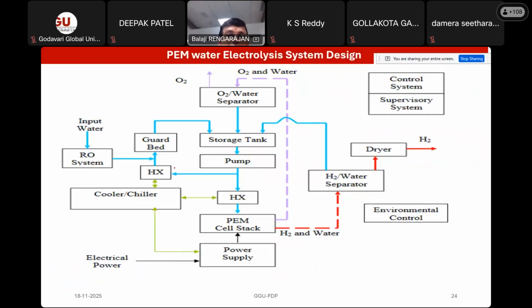And apart from the membrane and the electrocatalyst, there is a system, because if you want to generate hydrogen from water, you not only require the electrochemical cell, you also require other balance of plant, because you have to circulate the water to the cell at the anode compartment. When it comes out from the cell, it comes along with oxygen. So you have to separate the oxygen and the water, and again circulate the water into the cell. So you need a gas-water separator at both sides. On the cathode side also, you will get pure hydrogen, and it may carry some moisture, water vapor. So you have to separate the hydrogen from the water vapor, and then it has to be subjected to a dryer because it carries moisture. So you have to remove the moisture and get pure hydrogen. The pump, the electrical supply system and the gas-water separator system are all ancillary components required for the design of a PEM based water electrolysis system.